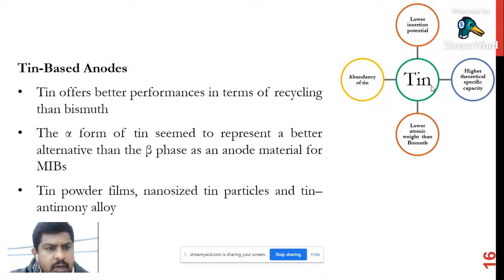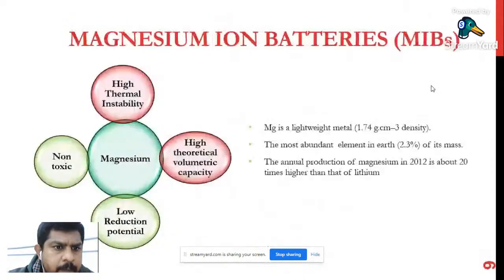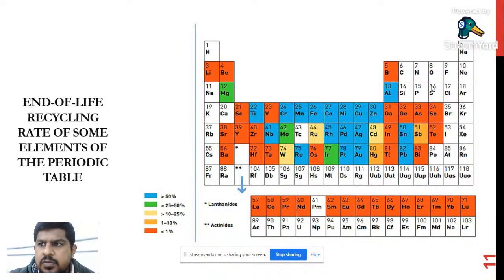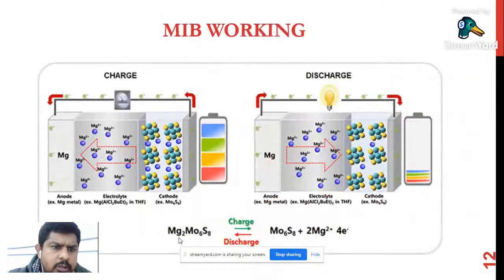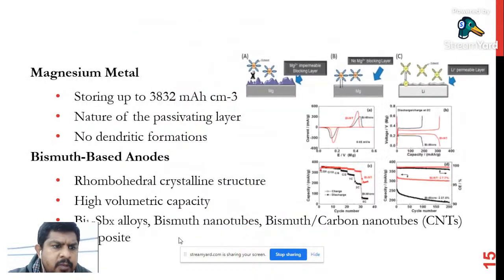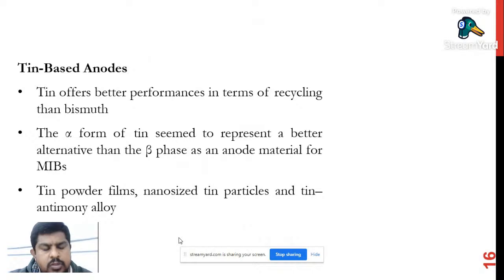If you see the recycling graph, with tin it lies in the range of 25 to 50 or more than 50%. But if you look at bismuth, it is less than 1%. So this is also a problem when we compare with bismuth anodes or bismuth alloy anodes. So tin-based anodes are better when you compare with bismuth based anodes.